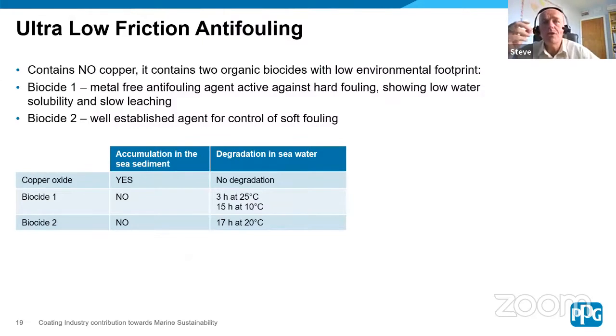The other thing is these organic biocides biodegrade very rapidly, whereas with cuprous oxide, degradation is not so apparent, and we do see bioaccumulation in the sea sediment. So we can see a transition away from cuprous oxide starting to appear.